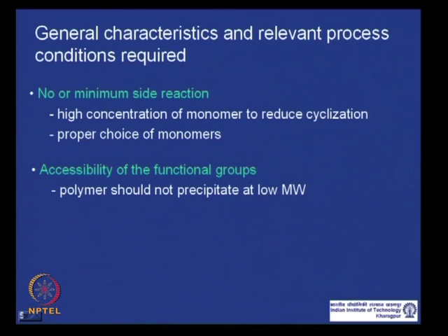We also saw that it is important that the functional groups are present during the reaction. If some molecules or oligomers are forming which get precipitated out of the solution, if you are doing the reaction in a solution, then the functional groups are not available to react. So, your solvent or medium should be such that your functional groups are always accessible to react.